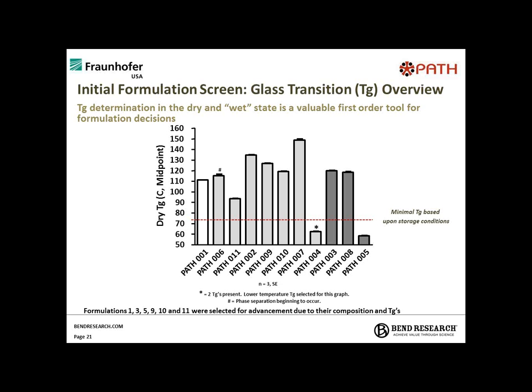It also tells us if we're seeing phase separation, if we are in fact getting amorphous dispersion of our particles during manufacturing, or if we're getting things that are separating, unstable, and generally poorly behaved. And this was a dry TG analysis we did of a number of formulations as shown on the screen. Our minimum baseline, if you will, for our TG, which was a go, no-go, was around 75 degrees Celsius. We saw that certain excipients, not surprisingly, the larger excipients, actually bumped up our TG. These were dispersions of salts, sugars, and polymers we used here to develop a rational approach for formulation development decisions.